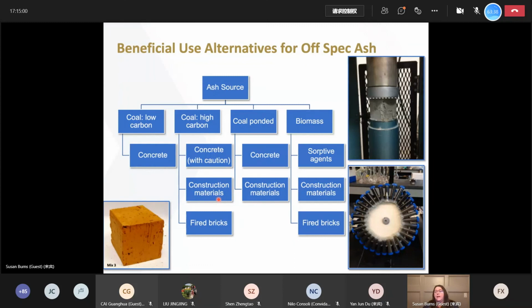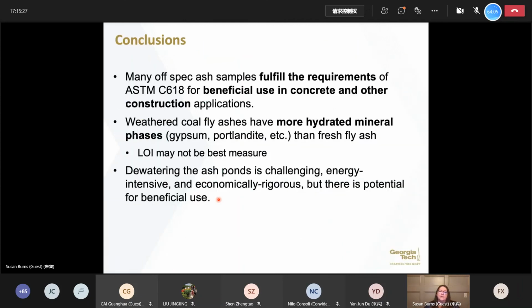The biomass ash, which I mentioned today, is not great in concrete. There's not any benefit to using it in concrete. It is, however, highly sorptive. Those activated carbon surface area numbers were very similar to what you'd see from a commercially produced activated carbon. So using that biomass ash as a sorptive agent in construction materials or also in fired bricks is a good application as well. And so what you'll see here is that many of the off-specification ashes that we deal with do fulfill the requirements of C618 for beneficial use.